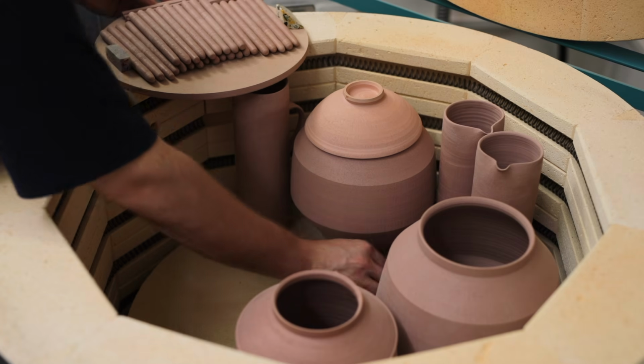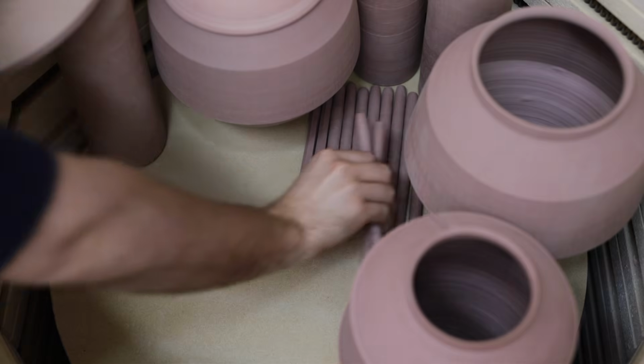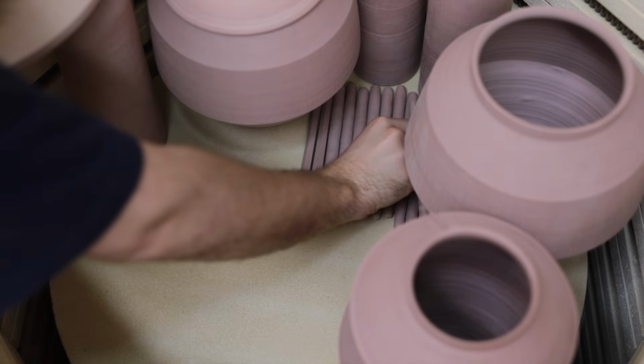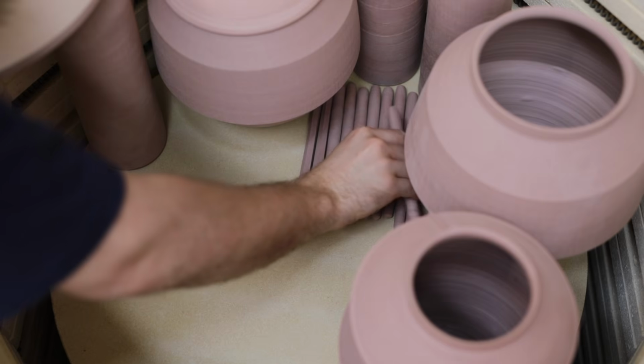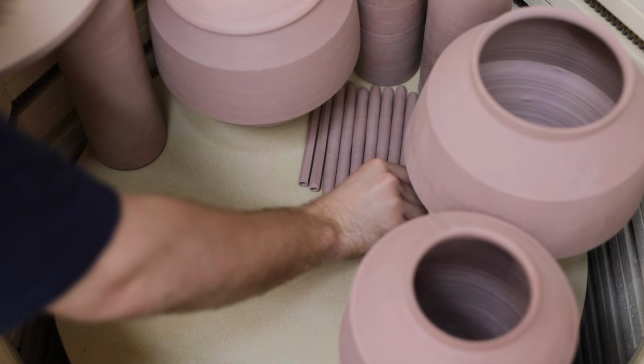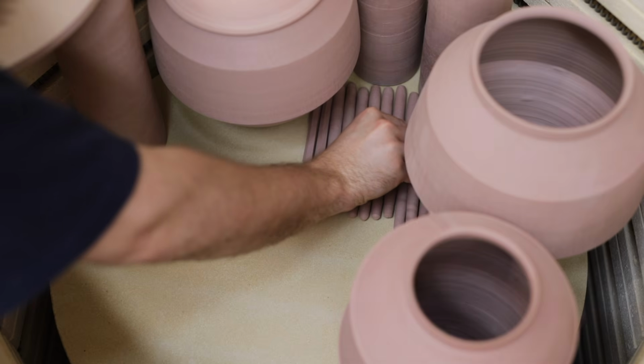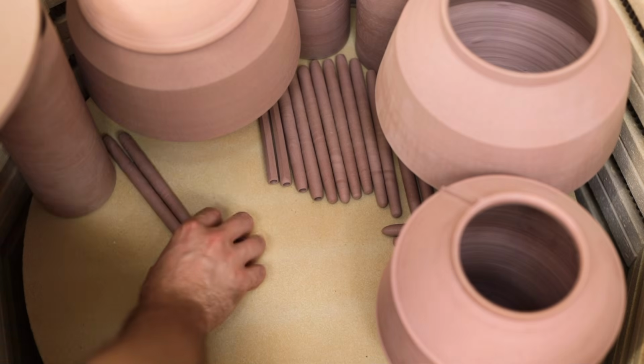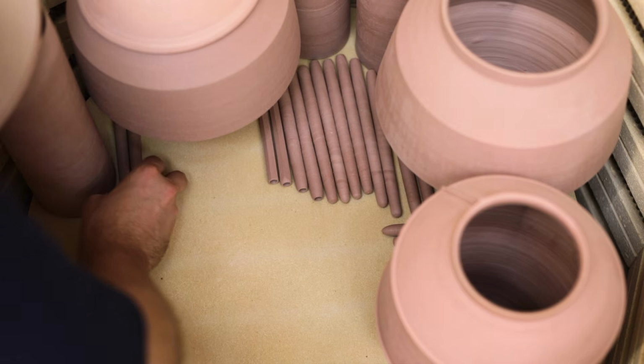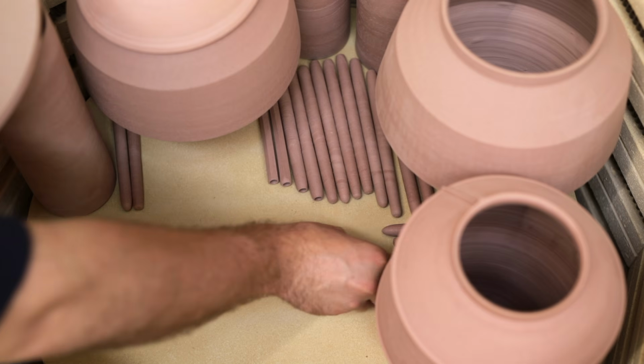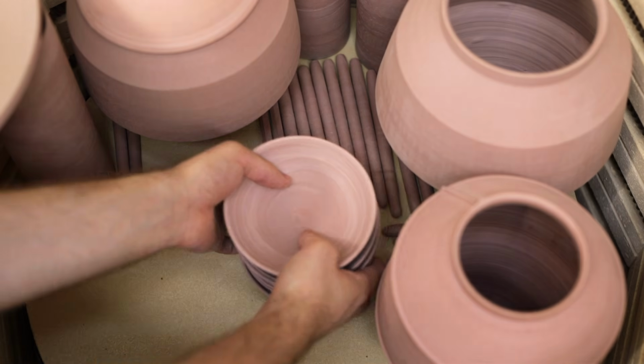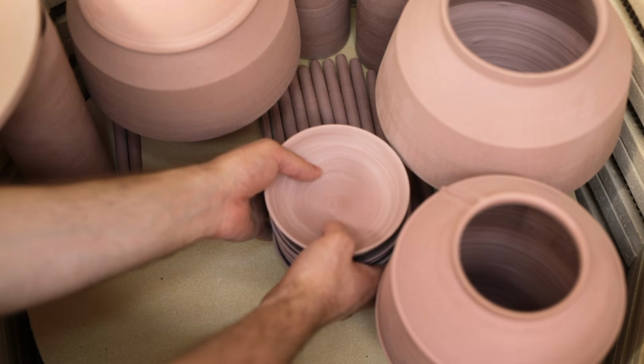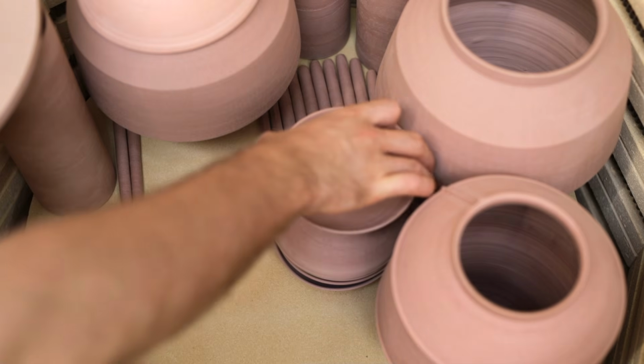This kiln has a capacity of 200 litres, and it's heated by the elements that are set into the walls. I fire this kiln overnight when I'm not there. It's programmable, unlike my gas kiln, and I can simply set the rate at which it climbs in temperature, which for this firing, goes to a maximum of 1000 degrees Celsius. You'll be able to notice the subtle colour change in the clay after it's been fired, but all of the pink hues that you can see at this point is just the iron content in the clay body. Once glaze fired, this pink tinge disappears almost completely.